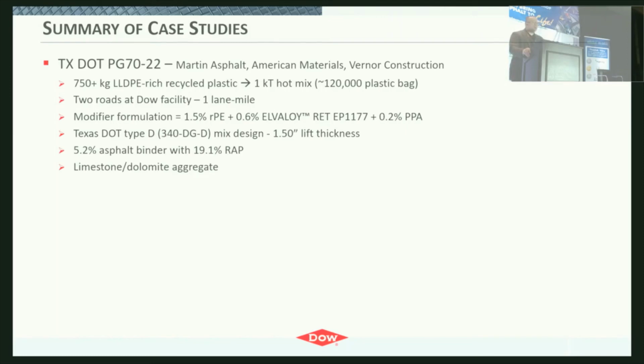We used 1.5% RPE, 0.6% Elvaloy, and 0.2% PPA. By incorporating the recycled material, we were able to cut the Elvaloy dosage by half. So overall, in this case, the binder was cheaper using the combined materials versus an elastomer only. This was a Type D mix design, 19% RAP, around 5% asphalt binder, and this was a limestone dolomite aggregate.